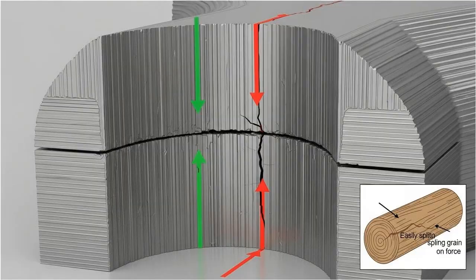Another fascinating effect of the layer-by-layer process is how the grains of the metal form. Heat naturally flows downwards through the previously deposited and solidified layers. This directional heat flow encourages the metal crystals, or grains, to grow upwards, perpendicular to the layers. This results in long, columnar grains that can stretch across many, many layers. These elongated grains, combined with the specific orientation of the martensite needles inside them, create something called anisotropy — a fancy word meaning the material's properties are not the same in all directions. It might be stronger when you pull on it along the build direction, but weaker and more brittle if you pull on it from the side. It's similar to the grain in a piece of wood: it splits easily along the grain but is very strong across it.